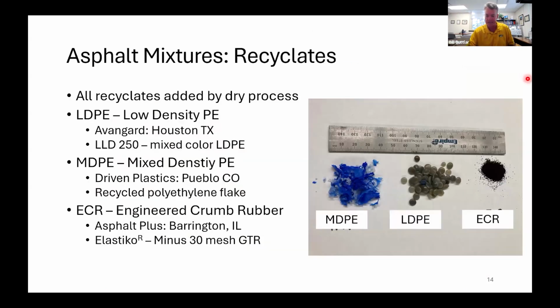Some pictures of what we tested. We had used the LLDP from Avangard before, so we went to a lower cost product. They think this is about 1/3 of the cost. So really nice to get a product that you can actually afford in the mixed low density polyethylene. So you can see some of these pellets were blue, gray, brownish. It's hard to see the blue ones here, but they were there.